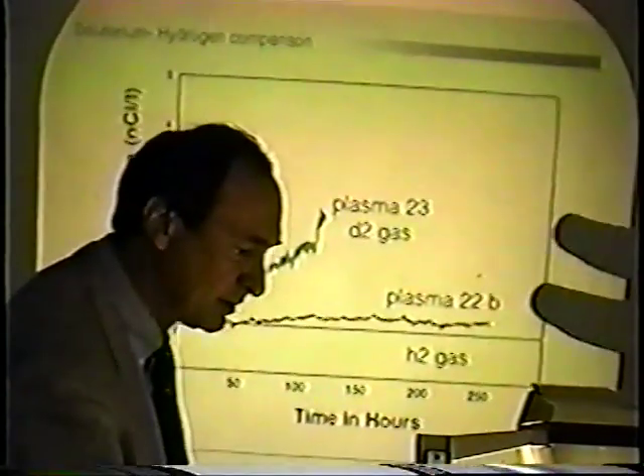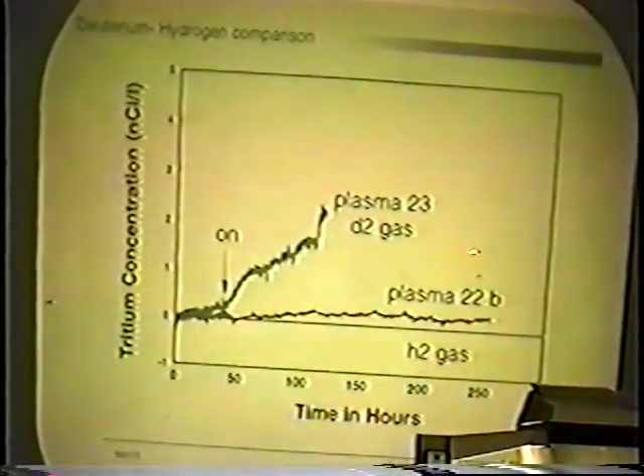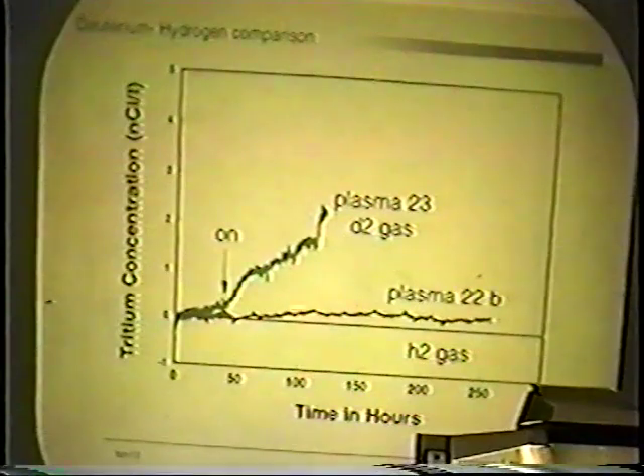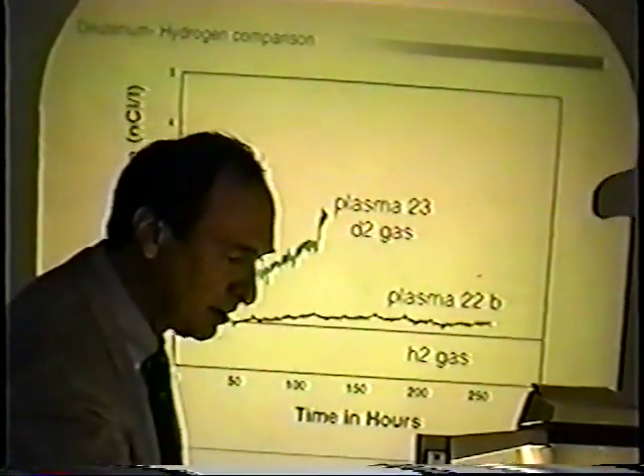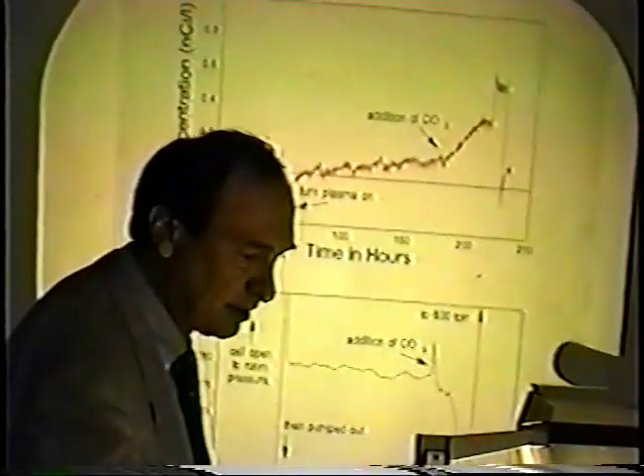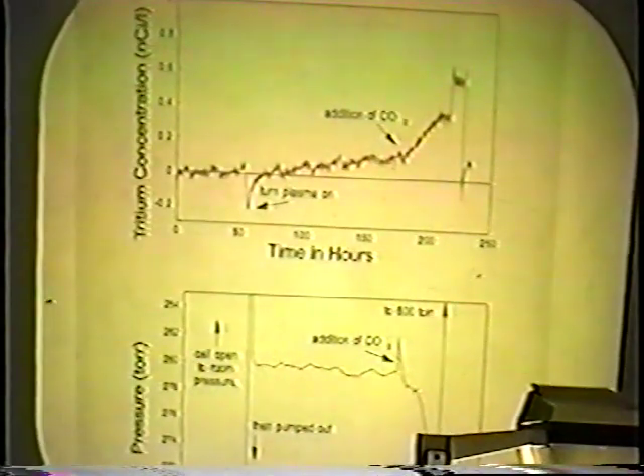A lot of people tried to encourage us to put in H2 gas additions, and we haven't seen any enhancement of tritium rates from those. They've been pretty much the background growth rate. And so this is just the H2 versus D2. And we've done this a number of times, and we really don't see any enhancement with hydrogen.